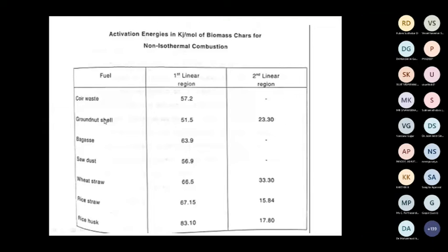You can ask one question: for groundnut shell, we also have a second region. The reason being, the char we are preparing at 900 degrees. Char means removal of volatile matter, and volatile matter can be removed at 900 degrees. When I subject groundnut shell to 900 degrees for the removal of volatile matter in the preparation of char, there is some surface melting of the char. So like the high ash fuels, here also pore diffusion control is present because of some melting characteristics over the surface. Gas diffusion control also plays a role. That is why groundnut alone gets a second region of linearity, similar to high ash fuel.